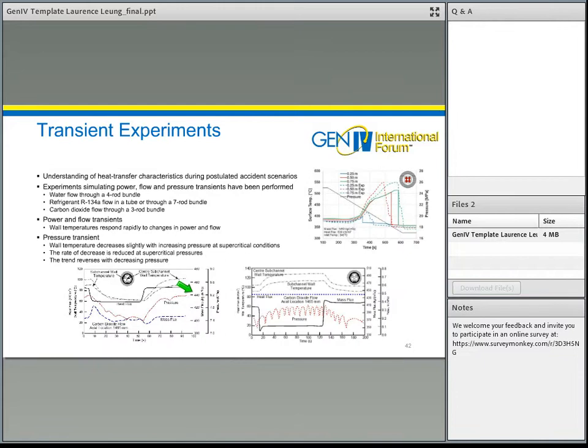So some of the transient experiments that we have collected so far, for example, in a four-rod bundle, you look at the pressure transient from a drop from a supercritical pressure down to subcritical pressure. What we find is that the cladding temperature, or the wall temperature at the rod, is actually quite low at the high pressure condition. When you approach the pseudocritical point, the temperature actually increases drastically. And this is similar to the film boiling condition at the subcritical region.